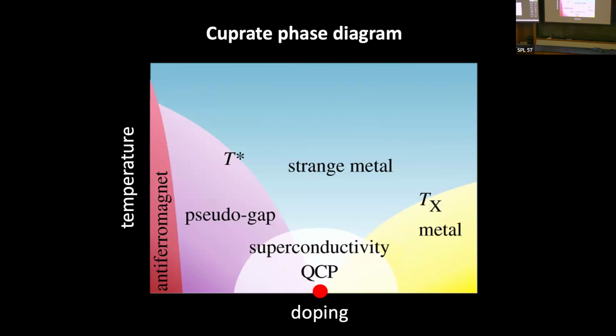But then if you dope the system away from half filling, quantum Monte Carlo starts to run into problems. There's something called the fermion sign problem. So it's hard to predict things at low temperatures. But that's where all the rich physics in the cuprates is. So for example, you have this famous d-wave superconductor down here. But even in the normal phase, like here and here, there's very rich physics. This is called the strange metal, where you have unusual transport properties. Here you have a pseudogap regime, where you have unusual spectral properties. So these are some of the things where the quantum simulators might shed light on the microscopics.